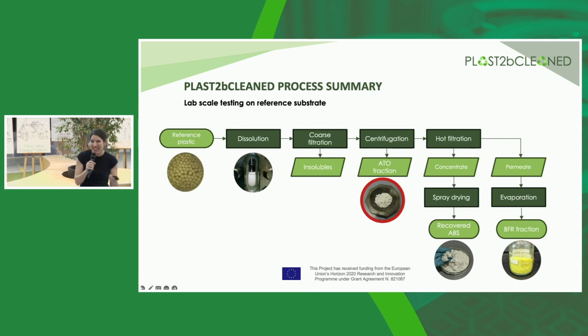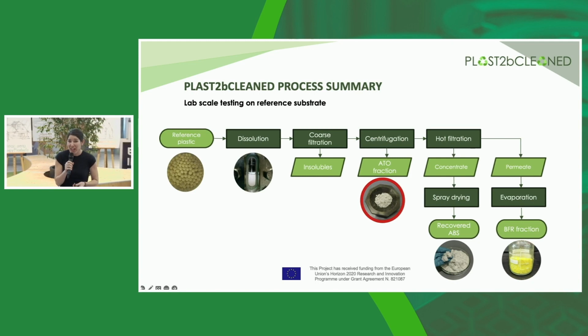So based on the test and process development we presented on previous slides, we came to a process flow of the Plast2bCleaned process as depicted on this slide. On the left-hand side, you can see the reference plastic that enters the dissolution process. After that, we perform a coarse filtration step where we separate all insolubles. Further, we pursue centrifugation to remove the ATO fraction, and we should also say that insoluble flame retardants will end up in this fraction. Then the polymer solution, ATO-free or predominantly ATO-free, goes to hot filtration, where we recover two streams.